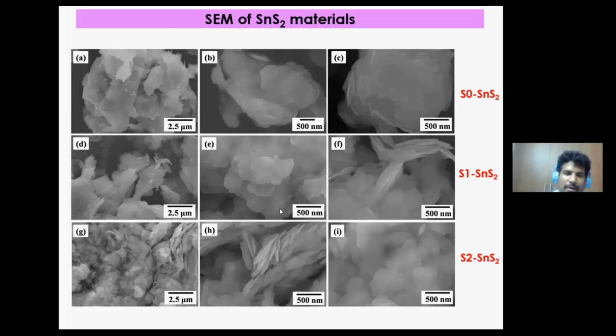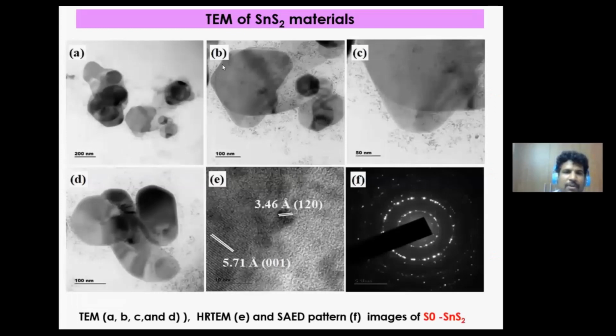So we wanted to take TEM to know more information about our synthesized material. So first we got TEM results of the SnS2 material that is synthesized using only oleylamine. Here you can see two kinds of particles. One is an unshaped contorted structure along with a secondary particle. So as I mentioned in the XRD, I gave an idea about the dissolution of tin disulfide. The dissolution is continuing for a long time, even when it is stored in cyclohexane.